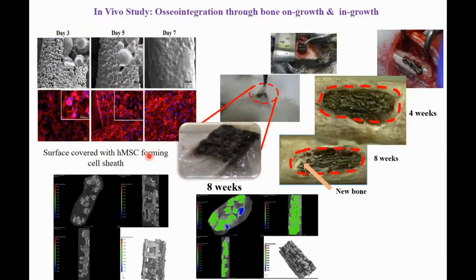We have done this in animal, and as you can see here, the location where the grafted implant has a very nice interaction with the bone, there you see significant bone ingrowth. On the other side, because there is a gap between the bone and the implant, there is no significant bone ingrowth. This shows that at the start there is a huge cell sheath, cell growth on the surface, and as you see from the 3D printed structure microCT result, there is bone ingrowth, and as you see there is also vasculature.